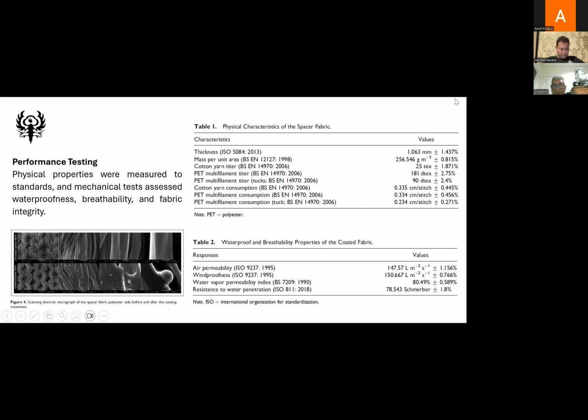And from the same visual, we can see at the left-hand side is the fabric construction. At the top is the fabric before coating, and the bottom is the material after coating. So you can see the fabric, the yarn and the fiber itself, before and after coating. You can see visually by SEM that the material has been coated.